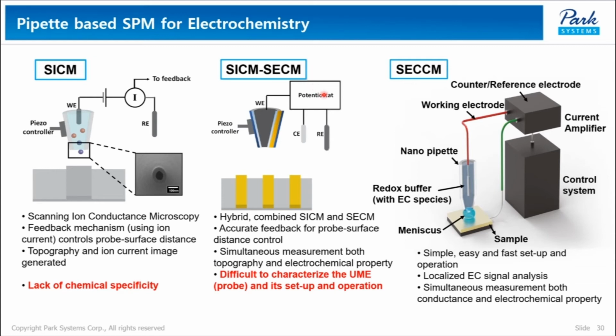In order to complement the shortcomings and combine the strengths of these two techniques, SICM-SECM has been introduced. There are two channels. One is to detect the ion current for topography, and the other is to detect the Faraday current for the EC response. The strong point of this technique is simultaneous measurement of both topography and electrochemical property. But it is also a bit difficult to characterize the probe and its setup and operation.